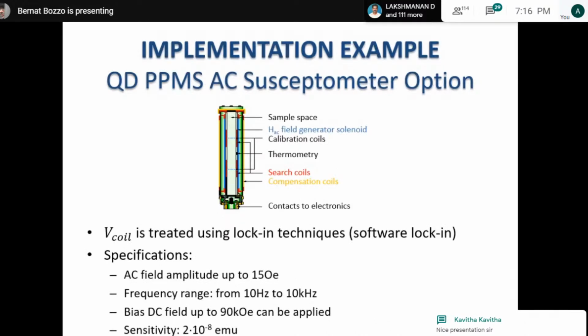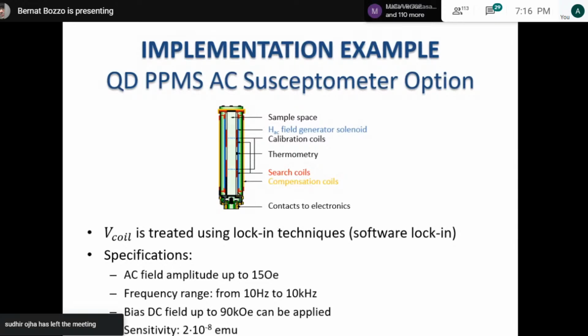So let me introduce now an implementation in the Quantum Design system that we have in our lab. Basically, this is a schema of the AC solenoid and the detection system. This is a somewhat more complex construction than the one I schematized before. You have in the center a sample space, and the blue part is the AC generator solenoid. The red parts are the pickup coils, which in this case are first-order gradiometers. We have some calibration coils which are used internally for giving a better accuracy of the generated signal, and some compensation coils that give our system better performance during the measurement. At the top is the contact to the electrode, and at the bottom is the contact to the electronics.